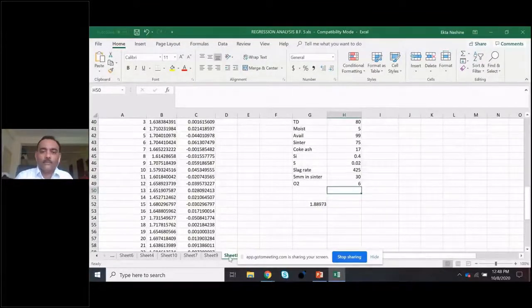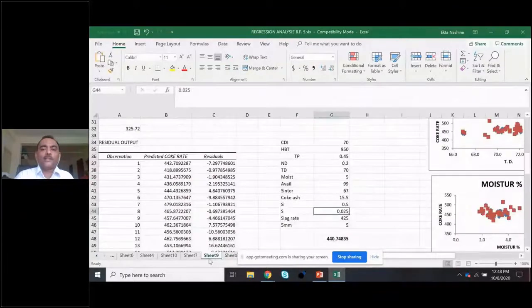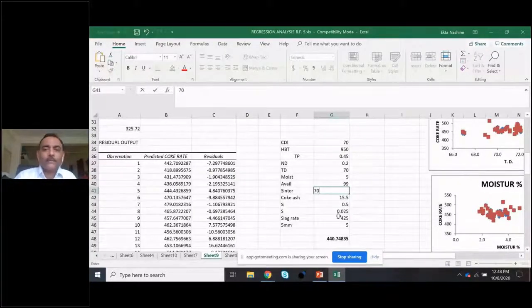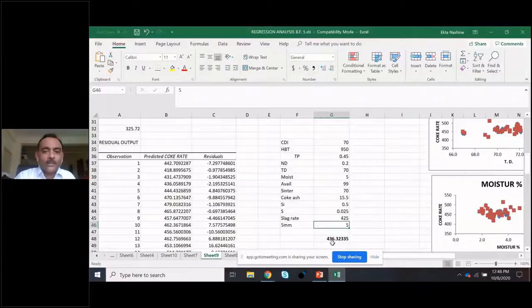Sheet 9. Here also, coke rate in the process is 440 kg. Meaning for producing 1 ton of hot metal, 440 kg coke is needed. Now, coke is the costliest material. We want less coke for producing 1 ton of hot metal. What will we do? Let's see. Can we improve sinter from 67 to, let's see, 70? What effect we got? 436. What it shows? If we improve sinter, coke rate will reduce.